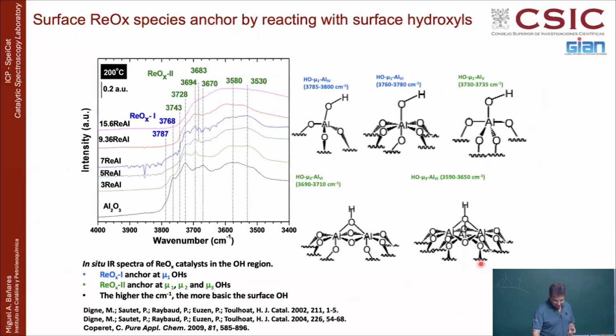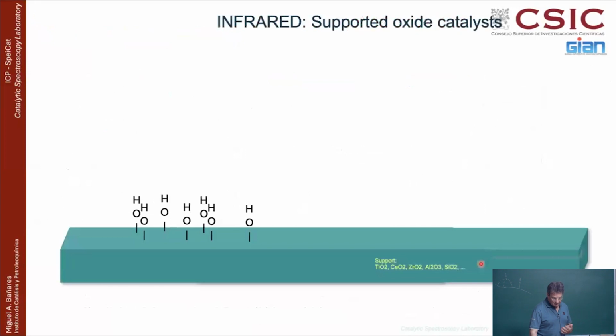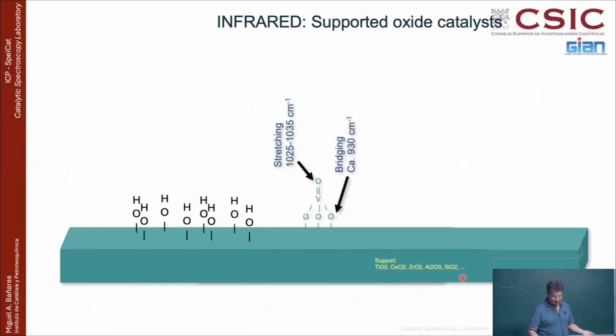Okay, so this is a repeated slide or very similar. So basically, in a support, you have hydroxyls that you can nicely see with infrared. And the support can be anything. I write here titania, ceria, zirconia, alumina, silica, can be anything. And then you disperse oxides. And these oxides will also have vibrations. And these vibrations will happen, for instance, for supported vanadium, depending on the support. The vanadyl mode will be at about 1000 plus wave number. And also the bridgings between the vanadium, the oxygen, and the cation of the support will have a vibration about 900 or whatever.